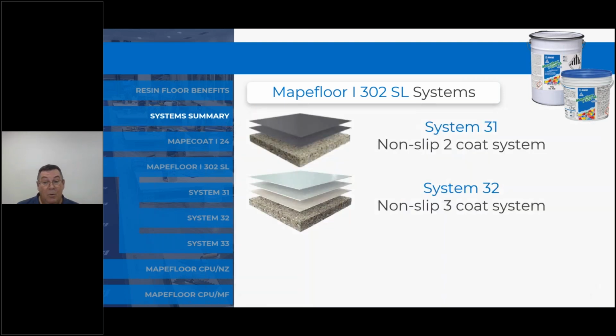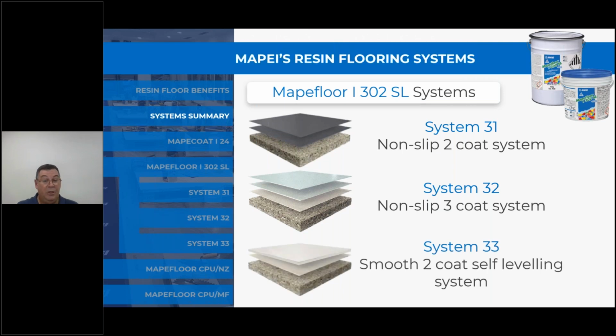So we look at system 31 and 32, non-slip two-coat systems, non-slip three-coat systems. From there, we move to the system 33, which is a true self-leveling floor system. So this is also two coats, but a primer and then a thick built up or bulked out resin system, troweled onto the floor, spike rolled and left to dry.